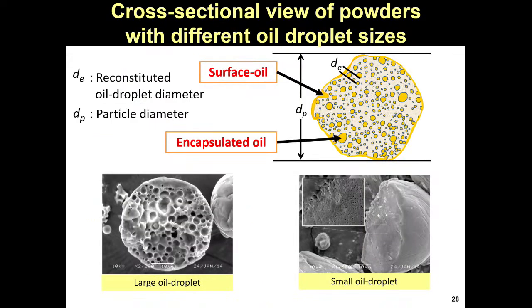This is a cross-sectional view of the powders with different oil droplet sizes. The powder size is about 6 micrometers. This is the large oil droplet case, and this is the small oil droplet. This oil droplet is about 2 micrometers, and this about 4 micrometers. The small oil droplet is about 0.2 micrometers. So when we check the powder structure, oil droplet size and powder size are very important.